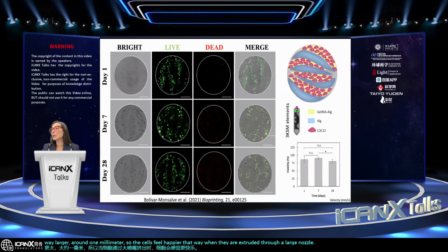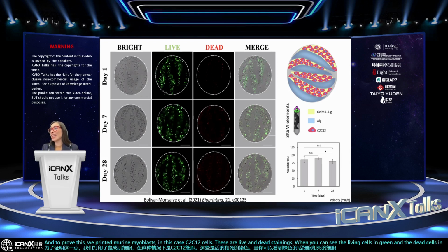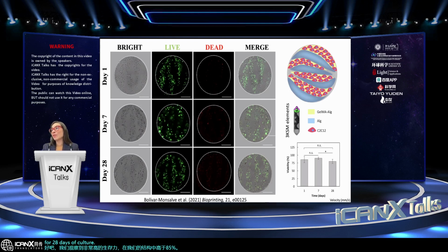And to prove this, we printed murine myoblasts, in this case C2C12 cells. These are live and dead stainings, where you can see the living cells in green and the dead cells in red. And we observe very high viabilities, higher than 85% in our constructs for 28 days of culture. And this makes sense, again, because the outlet diameter is huge, so cells are being accommodated by the laminar flow very benignly.